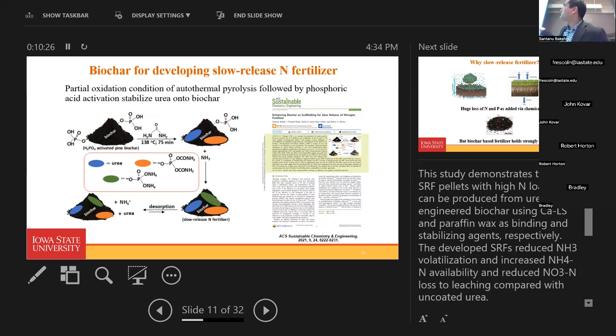That is the paper we published in 2021, Enhancing biochar as scaffolding for slow release of nitrogen fertilizer. In this study, we have shown that biochar slow-release nitrogen fertilizer can be produced with urea, paraffin wax, and calcium lignosulfonate as the binding agent. And the developed slow-release fertilizers reduce ammonia volatilization, increased ammonium nitrogen availability, and reduced nitrate leaching from the soil.